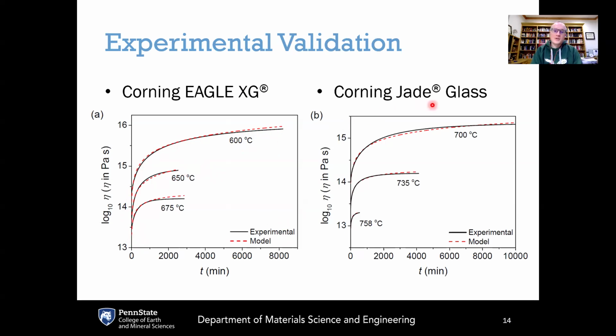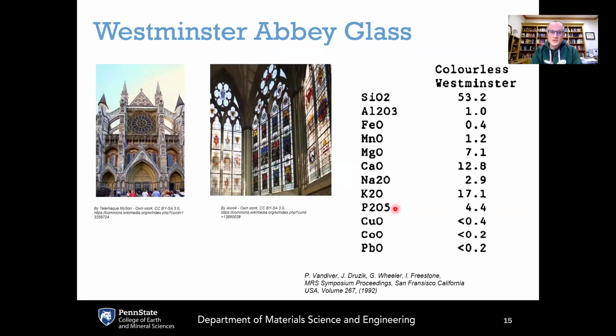Now, for a different glass composition here, Jade glass, you can see the same type of behavior. In each of these plots, the solid black lines show the experimental results, and the dashed red lines are the model predictions from that MAP equation. So it provides a really good prediction of how the viscosity is evolving over time for different thermal histories and for different holds at different temperatures.